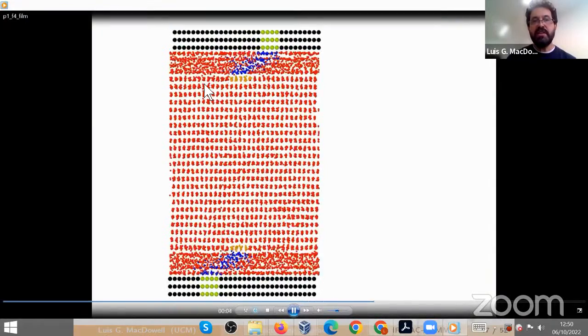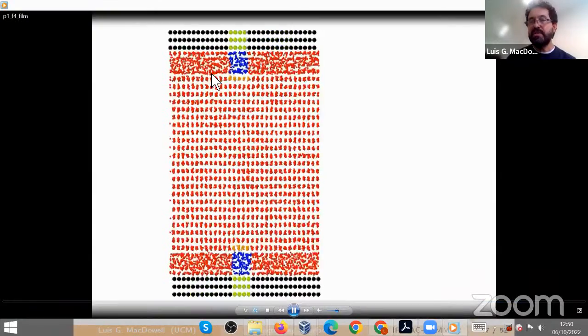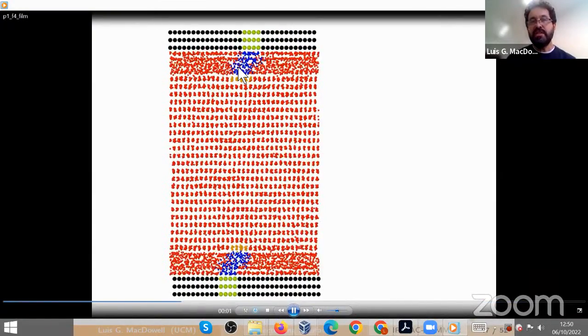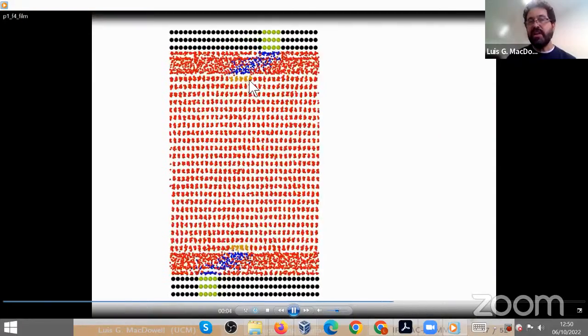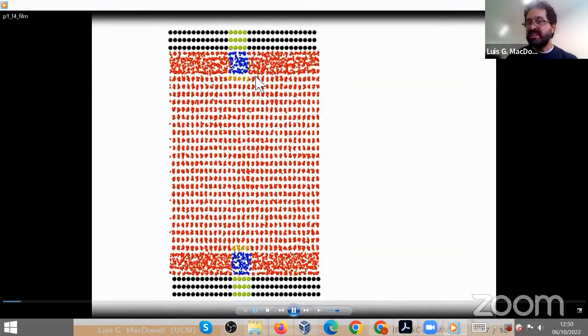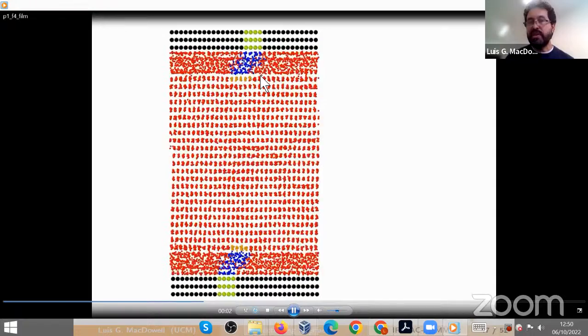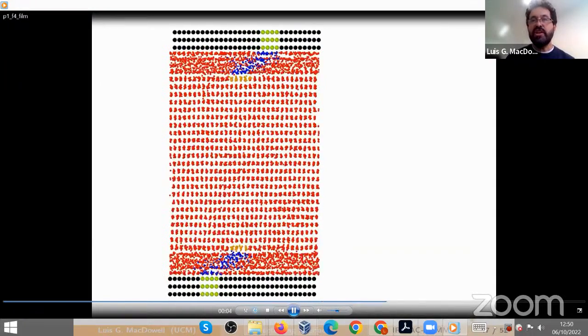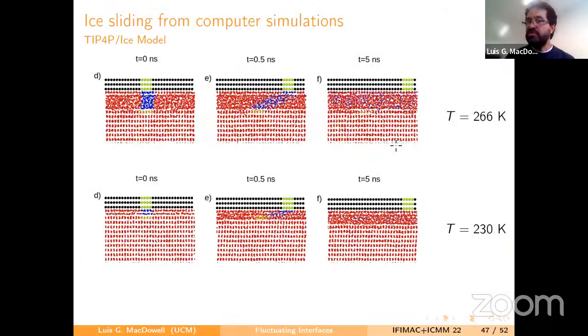Okay, what we see is that clearly a pre-melting film forms. And when you shear it, you get a clear pattern of laminar flow. This is Couette flow, exactly as expected in lubrication theory. So definitely we can show that at temperatures not too far away from 0 degrees, ice has an interfacial pre-melting film, and this behaves like a lubrication layer. So in that sense, Faraday was right.